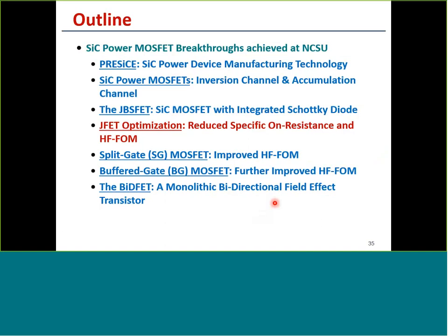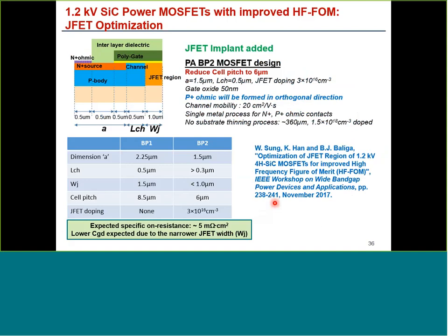Now I want to move on to the optimization of the JFET to improve the on resistance and improve the high frequency figure of merit for the devices. So in terms of the device structures, if we increase the doping in the JFET region, you can shrink the space, and that reduces the contribution from the channel because of the increase in channel density. In addition, making the space smaller reduces the capacitance between the gate and drain, CGD.